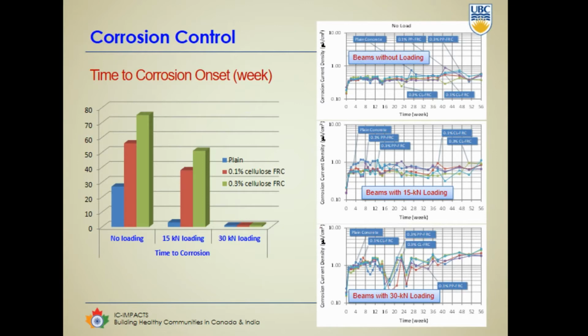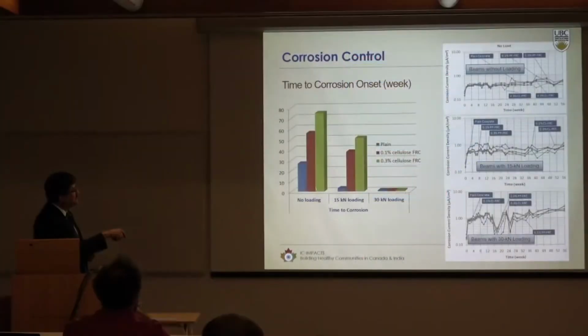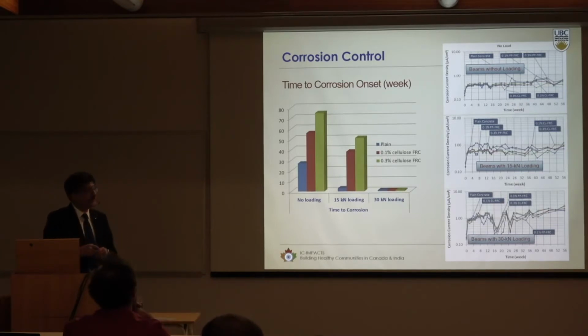You will notice that this is no loading, and you'll see that this is at different levels of cellulose. Our cellulose at 0.3% is absolutely delaying the corrosion quite significantly. When I have some loading on the beam, I see less of a reduction in the overall delay, but still there is a delay as compared to the plain system. And when I exceed the load beyond a certain point, the cracks have opened far beyond, and I will not see a benefit of cellulose internal curing at that point.